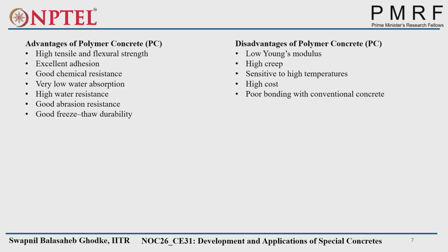Now let's see the disadvantages. We saw low Young's modulus and high creep. Creep means if you keep the same load continuously for a longer time, deformation will happen in the specimen. But in the case of the polymer concrete specimen, because of the low stiffness or low Young's modulus, the creep deformation will be higher. Then sensitive to high temperature: the chemical balance or the structure will change at high temperature. High cost, because the polymerization process requires high cost. Polymers are costly. Poor bonding with conventional concrete means if we put load on a composite of concrete and polymer concrete, then breaking will easily happen in between at the bond.